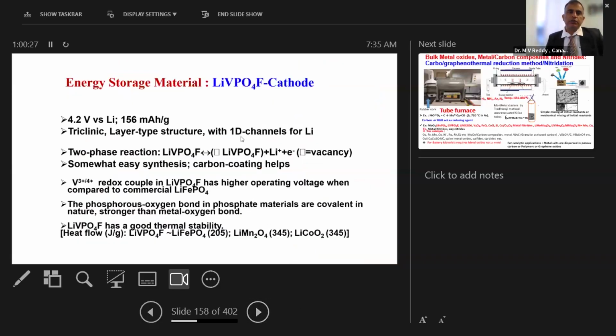So one particular example is lithium vanadium fluorophosphate. Always keep in mind that here the vanadium redox couple, 3+ to 4+, gives reasonably good capacity. In terms of thermal stability, I told you that this is really good when compared to lithium cobalt oxide.